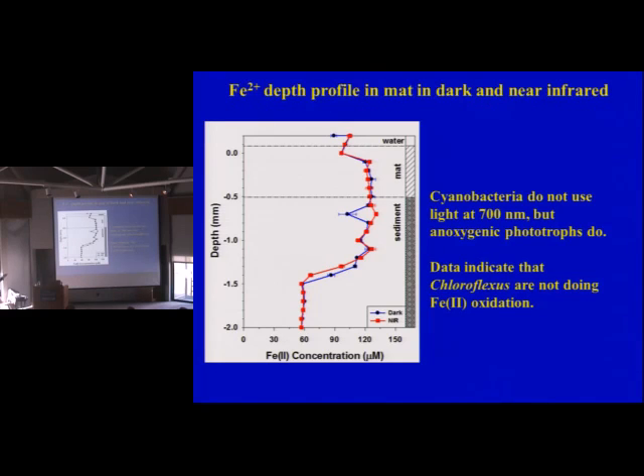Okay, so the question is, do we have any anoxygenic photoferrotrophs? Well, what we know of the photoferrotrophs, they will use the near-infrared around 700 nanometers. The cyanobacteria don't use that light. So here's a dark experiment in blue and a near-IR experiment in red, and they overlap. So the indication here is that the chloroflexes, although they're there, do not apparently do any anoxygenic iron 2 oxidation. All right? So that means that everything here in this case is due only to the cyanobacteria, not to anoxygenic